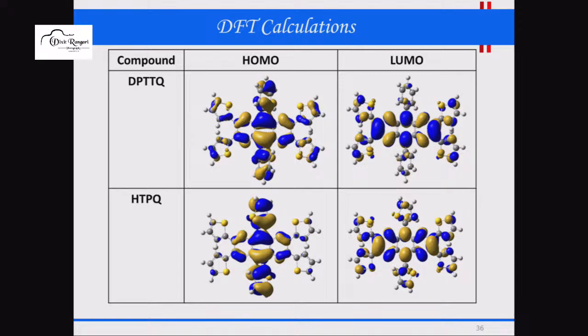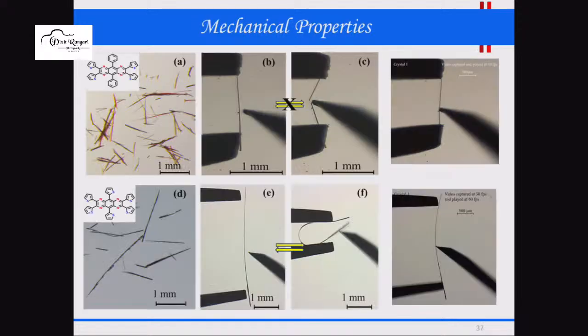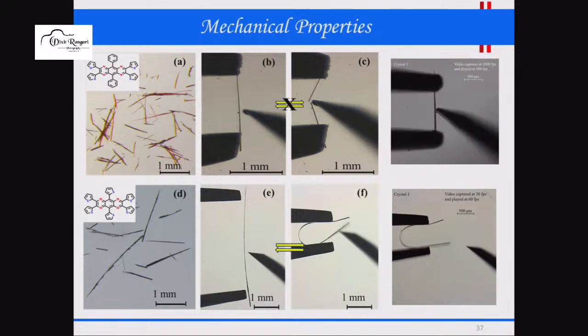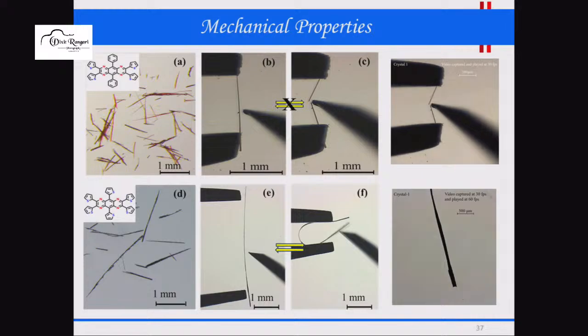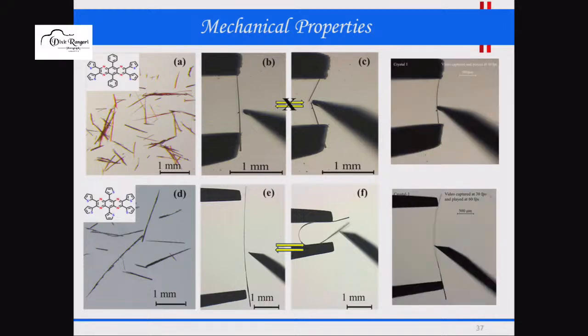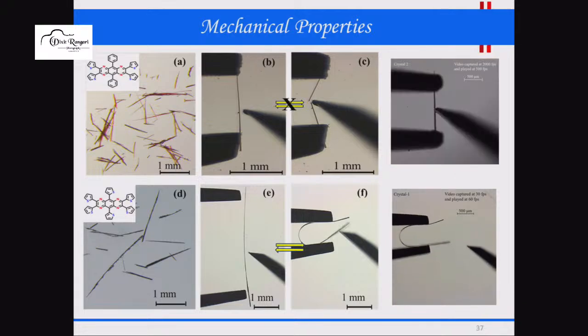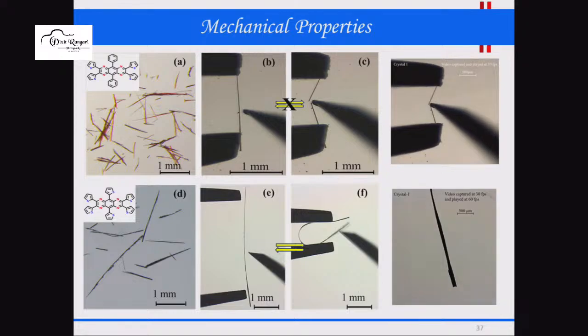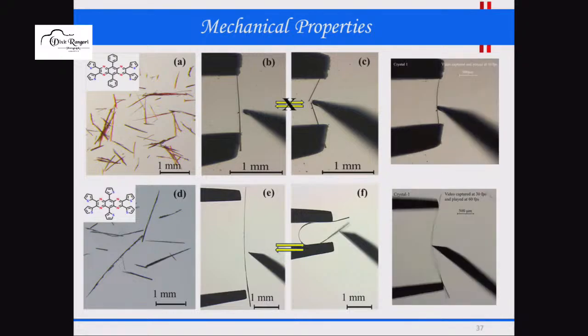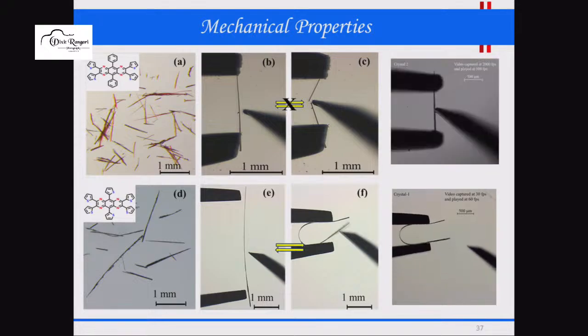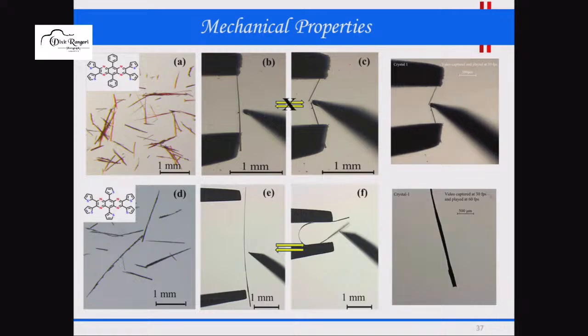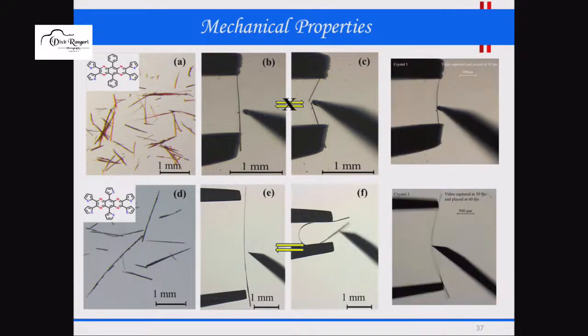So next, when we crystallized this molecule, we got nice long needle-shaped crystals, and then we collaborated with Professor Molla Reddy. We wanted to study the mechanical properties of this crystal. Now you can see in the next slide these two different molecules: the first has a phenyl group, and the second has a thiophene ring. When you take the phenyl-containing crystal with forceps and look through the optical microscope, the first crystal is brittle and breaks very easily. But the second crystal is nicely bending and coming back to its original position.